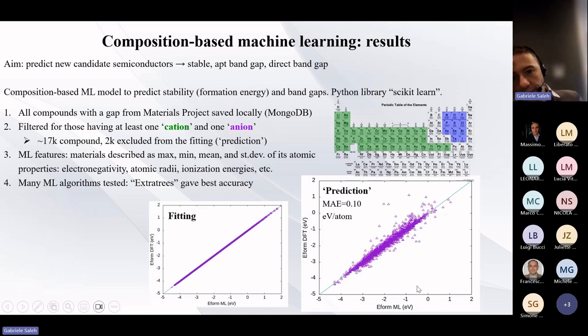So the great majority of them lie on this line. The mean average error is 0.1 electron volt per atom, which may not be good enough to make a perfect prediction, but it's good enough to apply screening to materials to exclude those that are certainly unstable. And it's also pretty impressive if you remember that these predictions are made just based on the chemical formula of the material. No other information is fed to the machine learning algorithm.